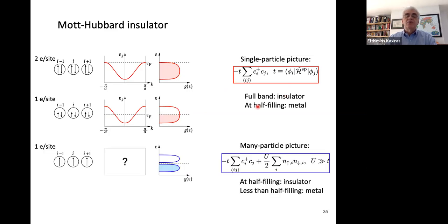So the idea then is that we need more than band theory. We need the many particle picture to describe this, for instance, using the Mott Hubbard insulator idea, where the bands split into subbands because of the correlated electron motion, as suggested very schematically here. This is not a realistic picture. It's just to show you that you can have one electron per site. That's half a band, and the lower half band is occupied with a band gap because these electrons cannot hop around because of the large repulsion energy when you have two electrons on the same site. So that's the idea of the Mott Hubbard insulator, going beyond band theory to try to address this.